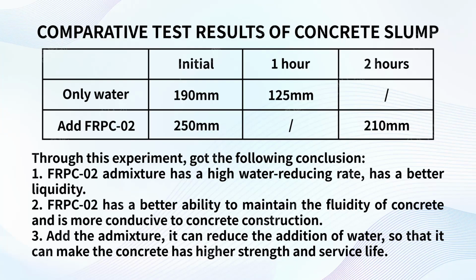Through this experiment, we got the following conclusion. 1. FRPC-02 admixture has a high water reducing rate and better liquidity. 2. FRPC-02 has a better ability to maintain the fluidity of concrete and is more conducive to concrete construction. 3. Adding the admixture can reduce the addition of water, so that the concrete has higher strength and service life.